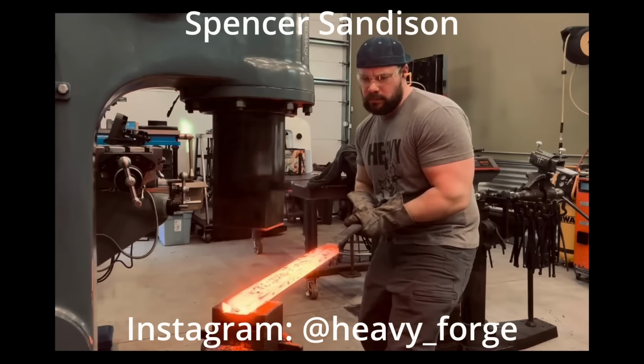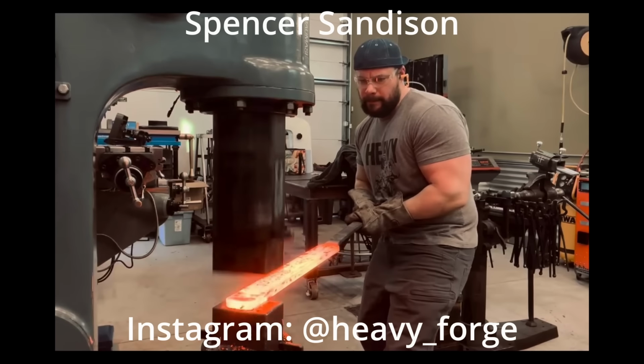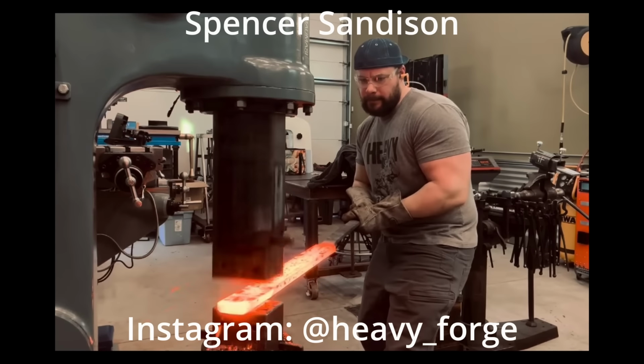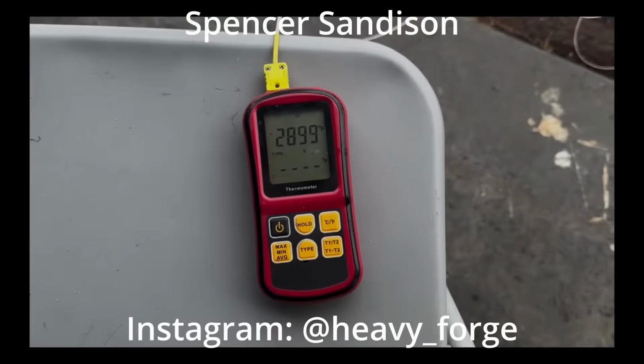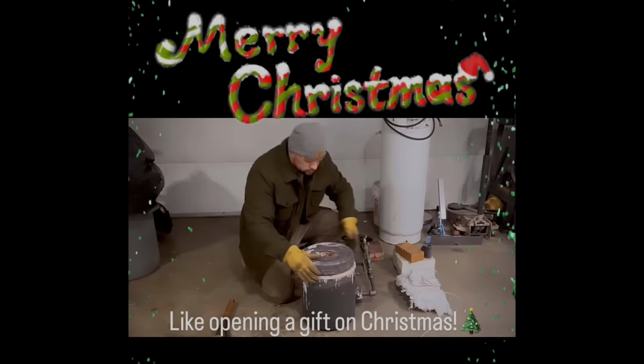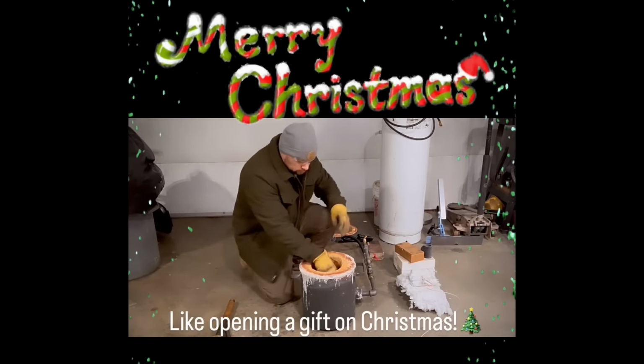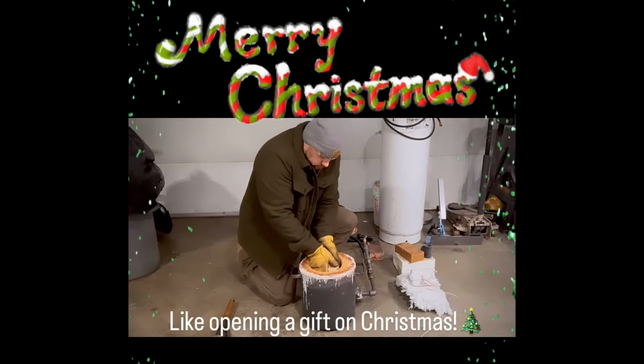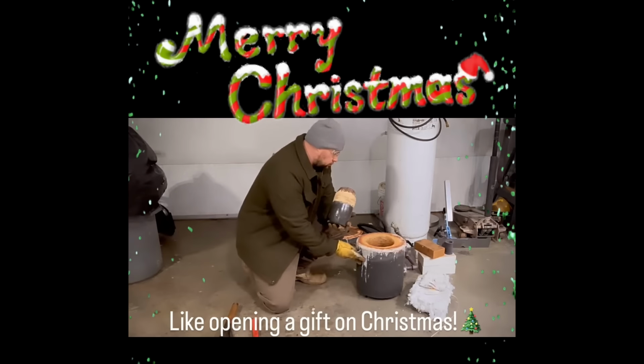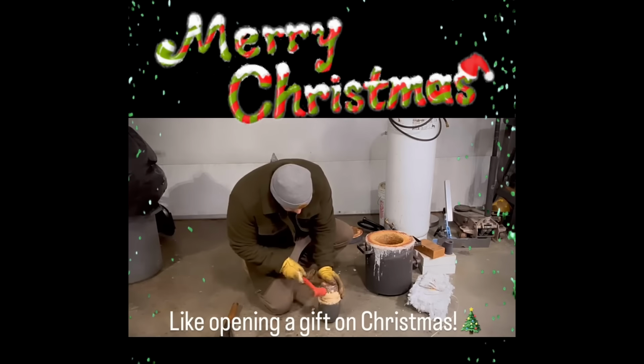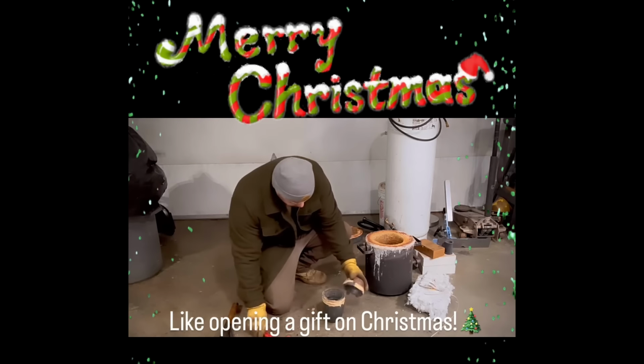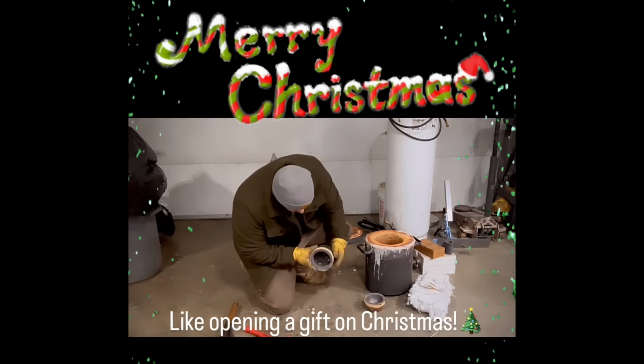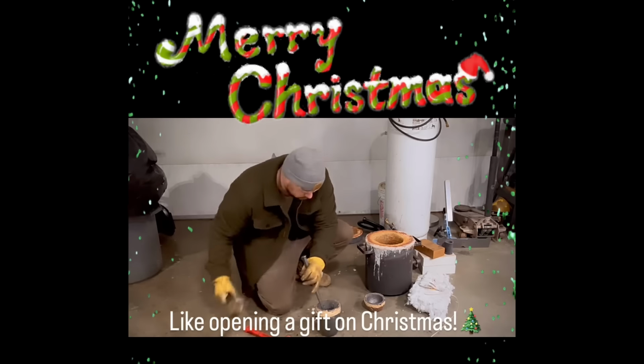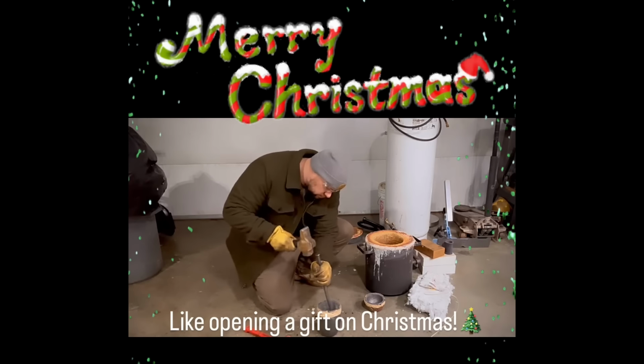I worked with bladesmith Spencer Sandison on this study. He has made Wootz in the past. He's very good at it. What he does is he starts with electrolytic iron flake. That's a high purity iron source. Then he adds pig iron, which is a high carbon, though also somewhat high impurity level type of iron. It's an intermediate product during steel making. They smelt iron ore with coke, which introduces a very high carbon content to turn it into iron. Then he also adds a little bit of ferroniobium as the carbide former.